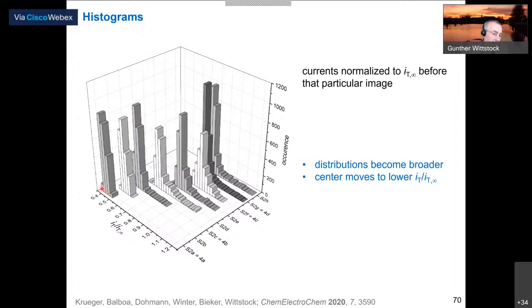These curves are kind of difficult to evaluate because both the distance and the reactivity may change. So we plot the normalized current for each image in histograms. So this corresponds to one image, and then we make a histogram of normalized current. We measure this current at far distance during that series of imaging, always just before the image, because we also have a small decay of the current during such a long experiment. To deal with that, we make the normalized current.